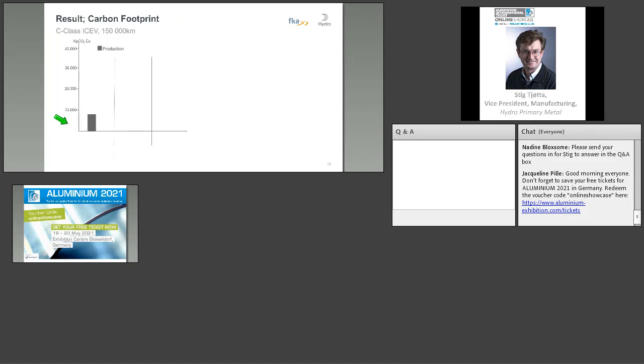To the result. The way we present the result here is first having the footprint from the build phase of the car, including all raw material. And this is for the C-class internal combustion engine vehicle. This is the steel reference with a footprint for the vehicle itself of around 8.5 tons of CO2 per vehicle. On top of that, we put the use phase emissions up to 150,000 kilometers, as I mentioned. And the first thing you can see here is, of course, that use phase emissions constitute approximately 3/4 of the total life cycle emissions, dominating the picture in a way.